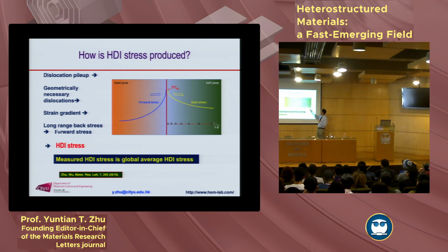If you have this stress concentration pushed to the boundary, on the other hand, there must be another force to balance it. You know, you cannot apply a force to the air. If you apply one force, 1 pound downward, you get an opposite force going upward to balance it. So on the other side of the boundary, there has to be a forward stress to balance this. At the boundary, it should be the same as N tau A, but in the opposite direction.